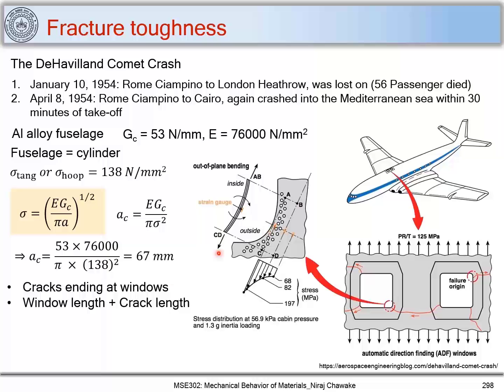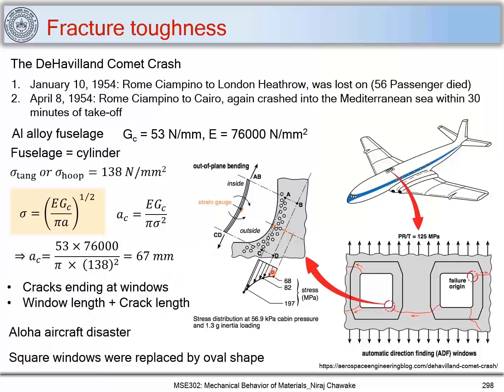This case study led to design changes. Because of stress concentration at the square windows, they were replaced by oval-shaped windows. You will never find square windows in aeroplanes today — this oval design criterion came directly from studying these two crashes. A similar situation can be found in the Aloha Airlines disaster, where unnoticed sharp cracks propagated drastically due to poor design.